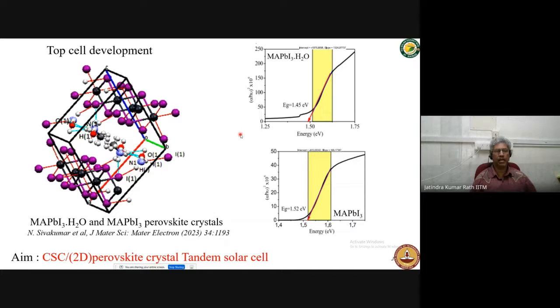We are also making the perovskite cells for top cells, and we don't want to do the ones which are going on in the market. We want to make crystalline perovskite cells, single crystals, and not polycrystalline ones. And this is in progress, and it's got band gaps. We have already got from like 1.5. It has to go up to 1.6, 1.7 to get the best tandem cell. They are going on that.